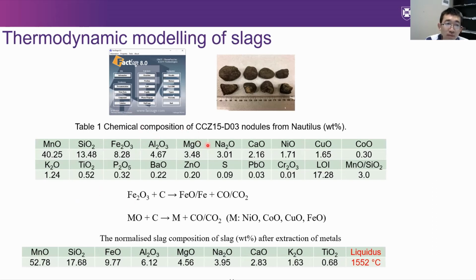So from the average chemical composition of the nodules, we pick up the major components, assume all the critical metals are fully recovered, and ignore the minor elements. We pick up the components in the bottom table and then calculate the liquidus temperature of the slag. It is around 1550 degrees, which is quite high. So based on this composition, we are going to further optimize it to achieve a lower liquidus temperature.